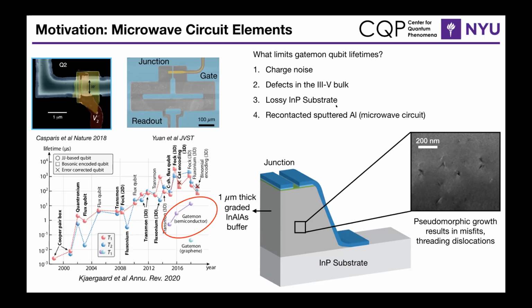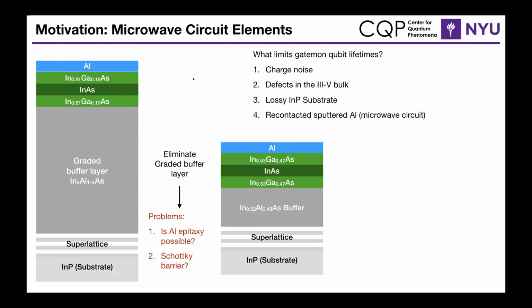Some other things are the lossy indium phosphide substrate. Indium phosphide is known to be piezoelectric and convert microwave energy into mechanical energy. And moving away from indium phosphide could be a good tactic in the future. And the last is this recontacted sputtered aluminum process, where you have this qubit island, but in reality, you're actually etching away everything around the qubit island, and then you're defining your microwave circuit down onto the indium phosphide substrate. And to do this, you have to have this etch and recontacting step, which can lower the quality of your microwave circuit.